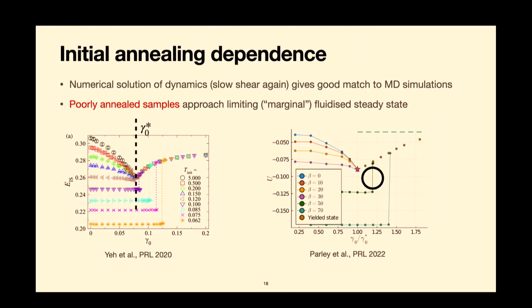Let's look at the better annealed samples, and here you see one of those. This is one where you start in a low energy, so that's a higher beta. And you see again, as in the simulations, in this case the yielding happens later. So you have to increase your amplitude and go through a sequence of steady states, and you get to a large amplitude before the system actually starts fluidizing. So that matches what happens in the detailed particle-based simulations that people have done. More interesting still is the dynamics.